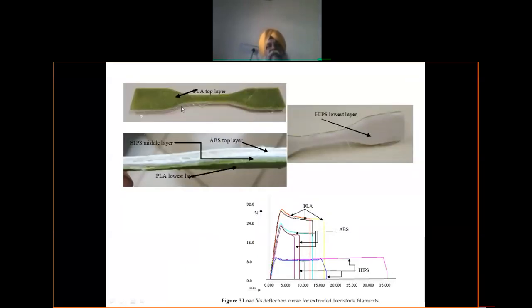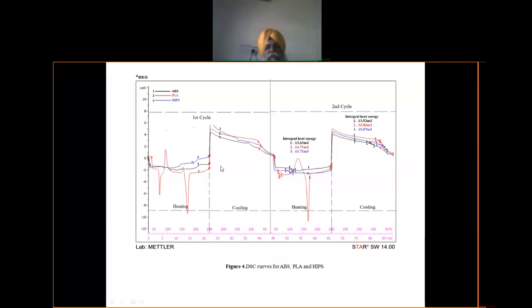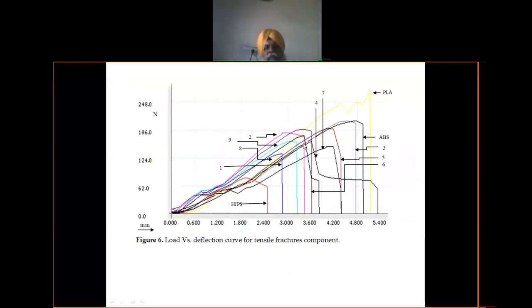I am interested in making this dog bone shaped component, with the top layer of one material, the intermediate layer of another material, and the lower layer of some other material. Then we tried to see the effect on their mechanical property and on their thermal property. If I look at this stress strain curve for the different compositions, I came to know which particular layer combination, with the lower, middle, and top layers of different materials, is going to give me the best mechanical property, right?